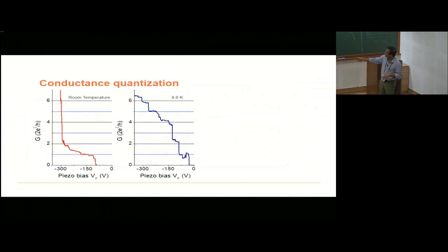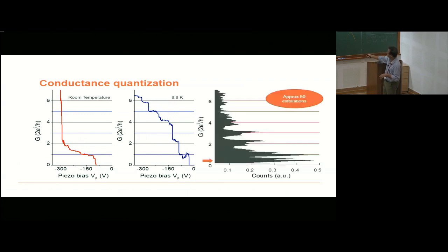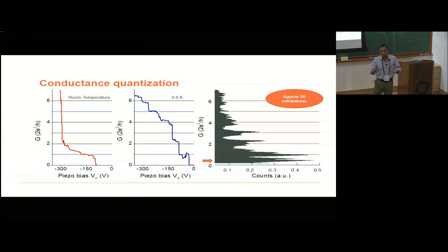So you can see even at room temperature, we have got very strong quantum confinement, and we see conductances of e squared by h. At low temperature, we get a series of them. If I put all of them together, there's something really interesting: we see peaks at integral multiples of 2e squared by h. However, something very interesting over here is that in addition to 2e squared by h, these are non-interacting peaks, we see another very strong feature at half of 2e squared by h, which probably indicates that the electrical conduction along the edges, or edge conduction, is spontaneously spin polarized.